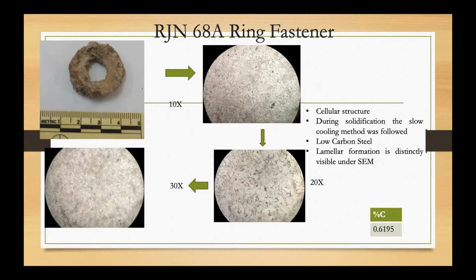This surface did not get hardened very fast, so it is not very brittle. It hardened according to the carbon that was absorbed by the cellular structure. And the cellular structures show it is a low carbon steel, and the lamellar formation is distinctly visible under the scanning electron microscopy.